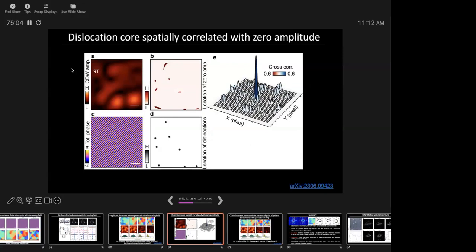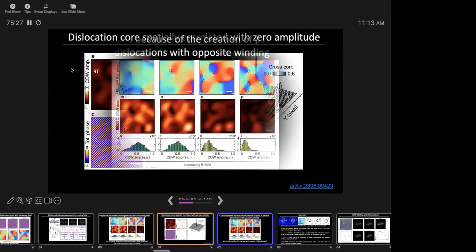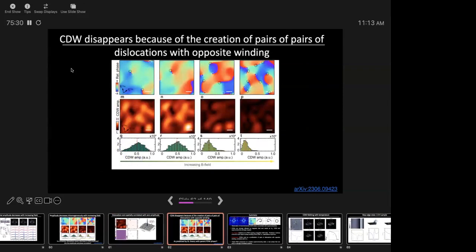This is, I think, at 9 Tesla. This is the amplitude map. These areas represent areas in the amplitude map where the amplitude goes to 0. And you can see that there's a direct one-to-one correspondence between the regions where the amplitude goes to 0 and the positions of the dislocations. So the CDW disappears because of the creation of these pairs of dislocations with opposite winding, and so that's that.